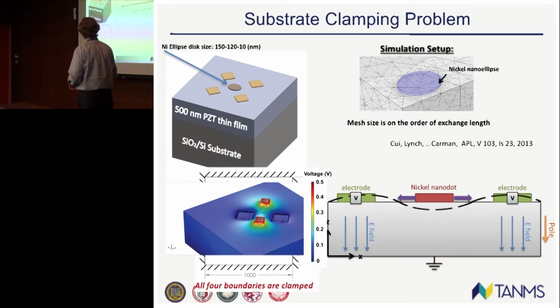So what he did, you see those 4 rectangles there? Those are electrodes. This is your single domain dot in the middle. And what he thought he could do is apply an electric field across those 2 electrodes. They would raise up. If you looked at the side image, these are the electric fields. They're raising up, and it's going to stretch this line segment in between, even though this is on a clamped substrate. And from that, he can actually stretch that magneto-elastic dot. So let's go into our models and see if it's possible.